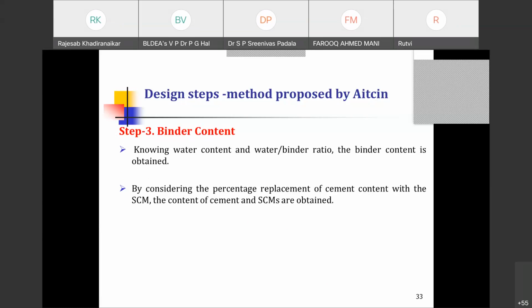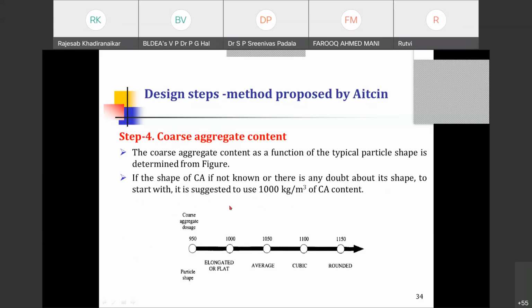Once you know the water binder ratio and water content, you can find out the binder content. Once you decide the binder content, you decide how much percentage of SCM, supplementary cementitious material, you want to replace. Then you need to go for the coarse aggregate content. It depends on the characteristics of your aggregate, particle shape, size, and so many things. If the shape of the CA is unknown, or you are not very sure, you can start with around 1000 kg per cubic meter of coarse aggregate content.